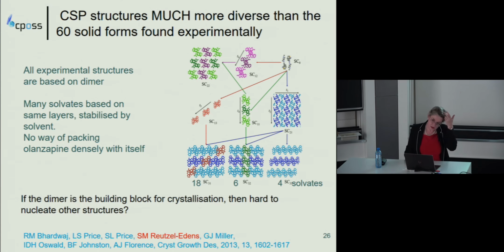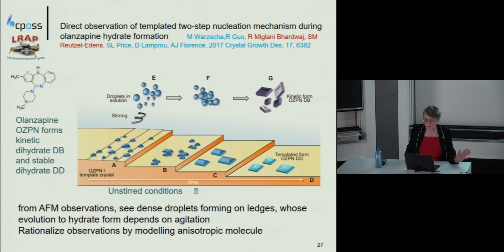And olanzapine, in the survey, they found 60 forms. A lot of them are solvates based on a layer structure which doesn't pack well with itself, and you get different solvents packing in there, raising questions about how olanzapine nucleates and grows.